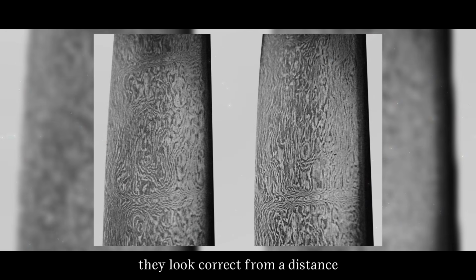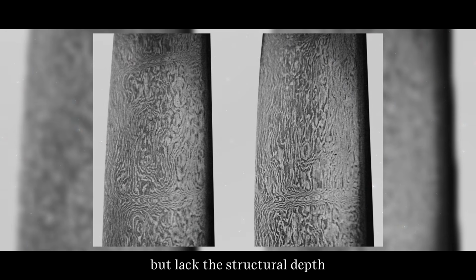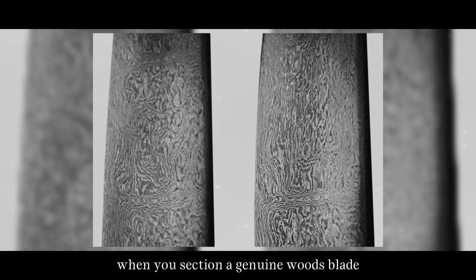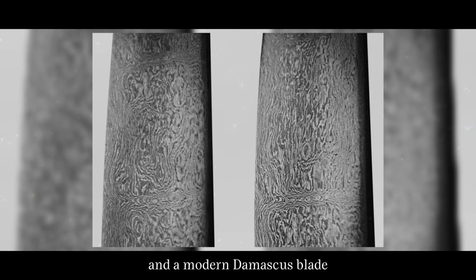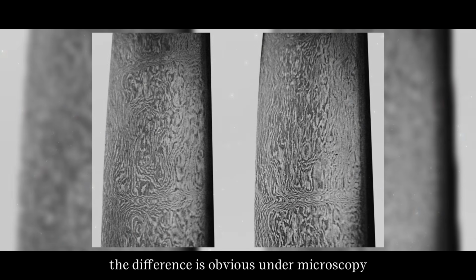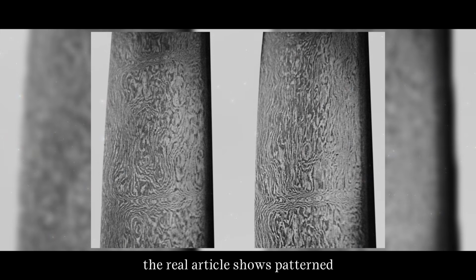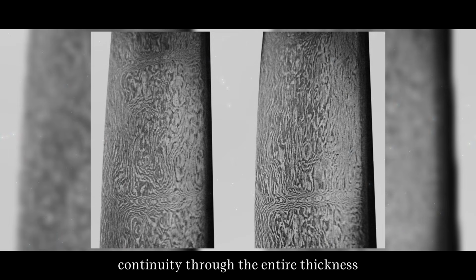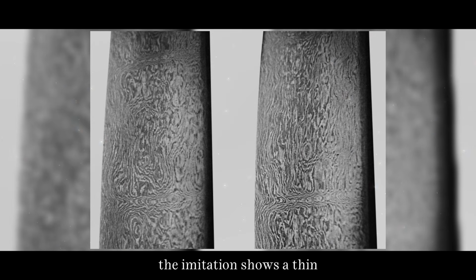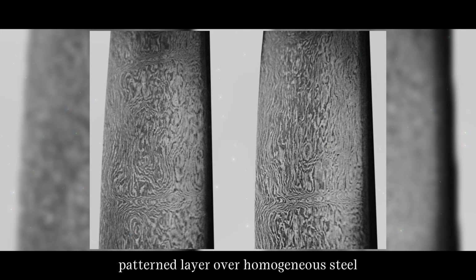Modern attempts to replicate this pattern often produce surface-deep imitations. They look correct from a distance, but lack the structural depth. When you section a genuine wootz blade and a modern Damascus blade, the difference is obvious under microscopy. The real article shows pattern continuity through the entire thickness. The imitation shows a thin patterned layer over homogeneous steel.